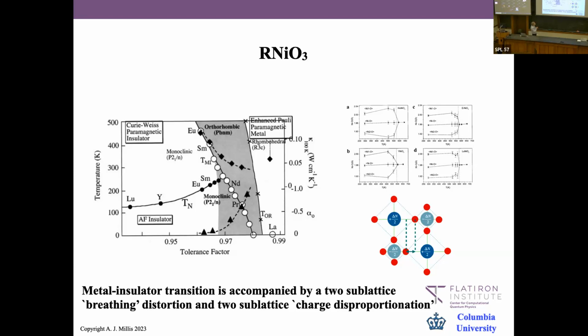The basic unit is, again, a nickel-oxygen octahedron. And when you go from the high temperature metallic phase to the low temperature insulating phase, what happens is you get a two sublattice distortion, where one nickel-oxygen set of bonds becomes shorter by some amount, the other becomes longer, but the average length doesn't change. You see that for a couple of the materials up here.